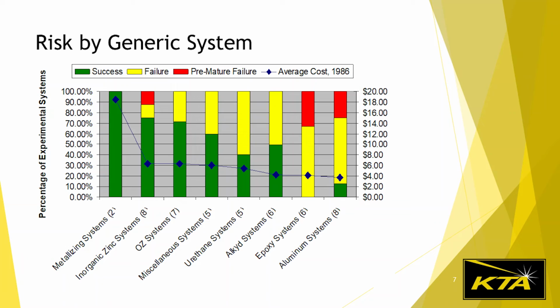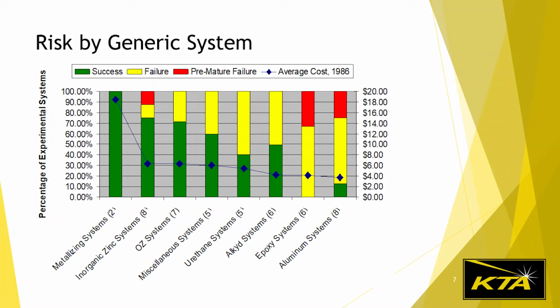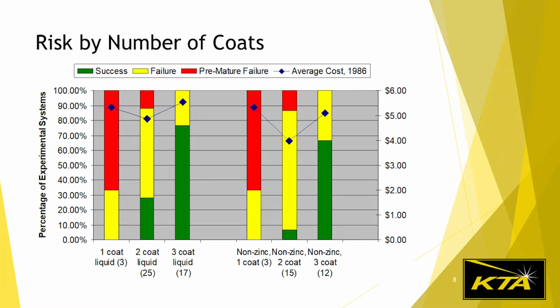So the next few slides are going to show some graphs like this. The blue diamonds represent average cost in 1986 dollars. Green represents average success rates, and yellow are average failure rates. Red represents premature failure. So as expected, the metallizing systems, they had the highest rate of success. They were about $12 more a square foot. So, hundreds of thousands of square feet on a structure, that could add up pretty quick. The zinc systems performed very well. The greatest risk was epoxy and aluminum systems. The 3-coat systems perform much better than 2- and 1-coat systems. Something of note from this graph is the 1-coat system, although more expensive than 2 and just about the same cost as 3, had the highest level of premature failure.